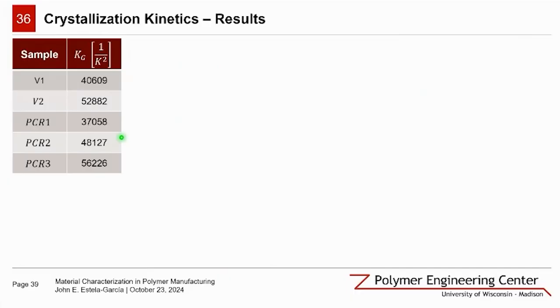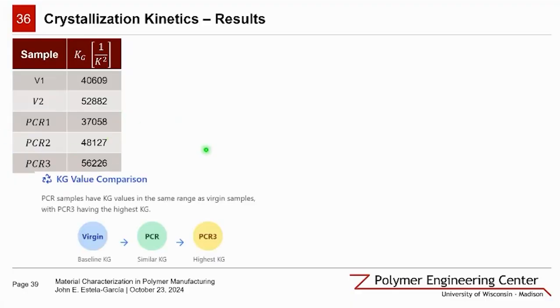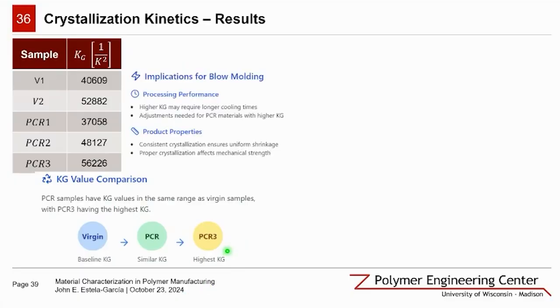So on the left here, we're showcasing our Nakamura coefficient values, representing the energy barrier for crystal formation. And it shows that the PCR samples generally fall within the range of the virgin materials. However, again, PCR3 is exhibiting a very high Nakamura value, indicating more significant energy requirement for initializing crystallization. And these findings have direct implications for blow molding processes.